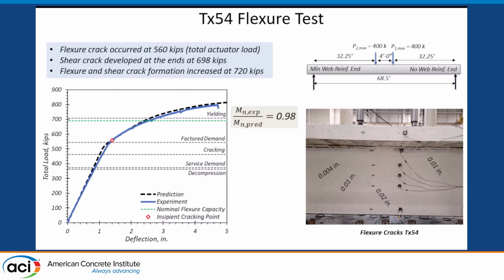And we did see the first sign of a flexural crack just above factored demand loads. So we felt like that was a pretty good outcome, that up to factored loading, we did not see any flexural cracks forming. As we continued on up, we see the green dash line, which is our nominal value that we're getting from our code prediction, and then we kept going beyond that. It's a little hard to see the photo here, but the cracks are very tiny, distributed cracks that we're reaching at this high load, well beyond the factored load.